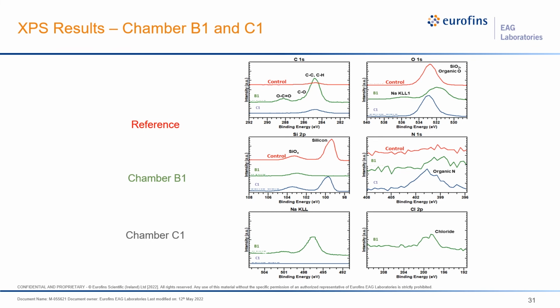And we can do this for each of the different types of elements we want. Here we're looking at the oxygen, here's the nitrogen. The silicon, you can see that there's a silicon metal and then there's SiO2. And you can see these are present in the other chambers as well. And so for something like the sodium, if it was a small peak, we could actually go into this binding range here and, for instance, run for a longer period of time over this smaller area and detect trace amounts of the chlorine.